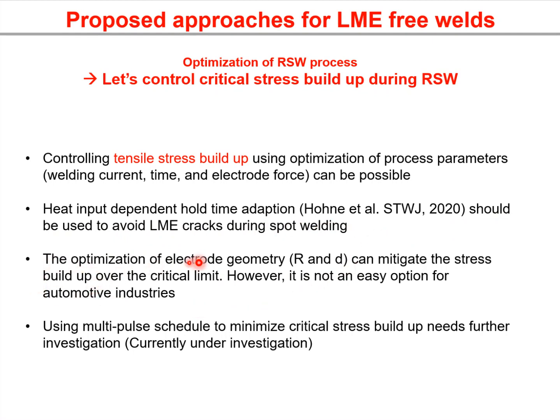The optimization of electrode geometry can mitigate the stress buildup over the critical limit. However, it is not an easy option for the automotive industry to adopt. Using multi-pulse schedules to minimize the critical stress buildup needs further investigation. Let's control the fraction of liquid zinc, alpha Fe-zinc layer, grain boundary energy, and stress buildup for LME-free spot welds.